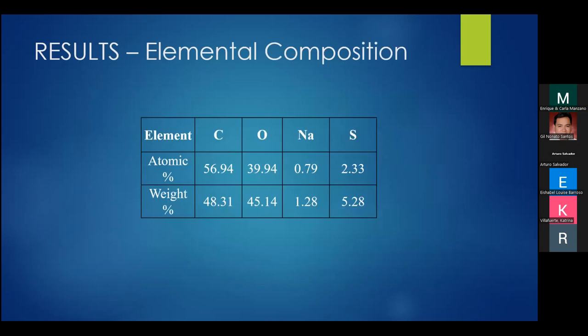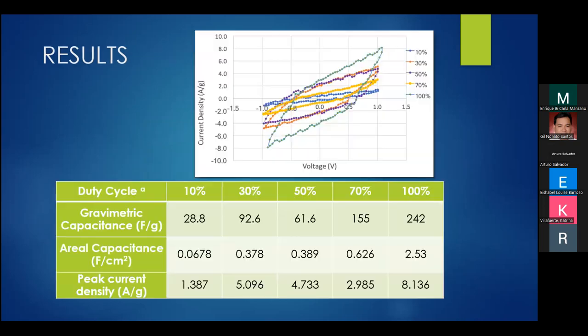For the EDS results, we were able to detect sodium on the surface and so forth. So this shows effective doping of the conducting polymer with NAPTS.